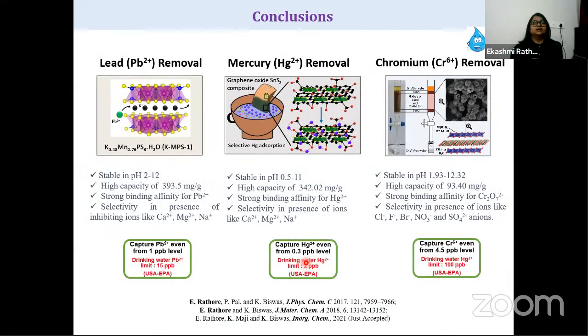So in conclusion, I have tried to remove heavy metals like lead, mercury, and chromium. All of these are working in a broad pH range with very high capacities and strong binding affinities for various heavy metal ions, and with high selectivity towards the other metal ions present in the water. And the most interesting part, the novelty of my work, lies in this: my materials were able to remove contamination from such a low concentration.